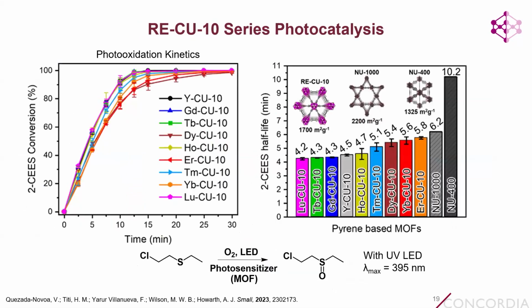And so now we can take a look at the photooxidation kinetics. So we can see here the conversion versus time profile for all these analogs of Cu10. And we can see the half-lives for these reactions. And what we see is that for some of these MOFs, particularly the ones where that linker to metal energy transfer is taking place, we do see slightly slower reaction kinetics, so slightly longer half-lives, confirming that although it doesn't make a huge difference, the identity of the rare earth element is important when considering designing these photocatalysts for this application.